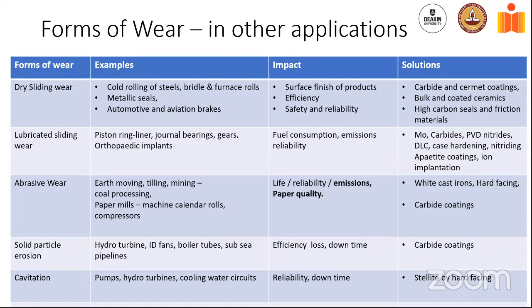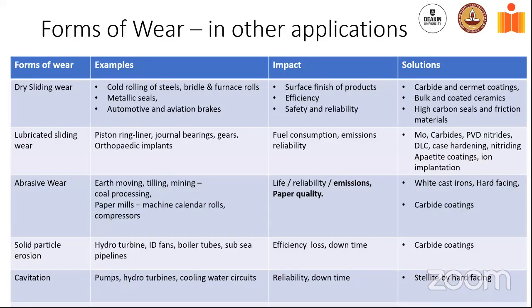Maybe all aesthetic, but are there other reasons why you want to worry about sliding wear? Metallic seals, for example, are used in pumps and compressors to keep hazardous gases at bay and ensure that they stay where they need to, or to have pumps and compressors work without oil so that there are no oil fumes, so that these oil fumes don't get into the pharma industry reactors and contaminate the medicines that you buy. So if you don't want oil floating around in a pharmaceutical plant, you need pumps that can work without oil. And some of those use metallic seals, and those metallic seals work brilliantly under sliding and impact conditions, primarily because of the materials that are used.